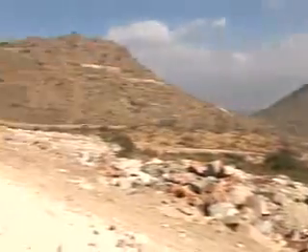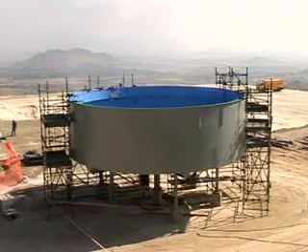Plant operations is a traditional concentrating plant for PGMs. We've got an off-take agreement for the PGM concentrate with Impala Platinum. We also produce some chrome as a by-product and have take-off agreements for that in place as well. We're building a milling and flotation plant, which consists of all your metallurgical units — your crusher section, milling, silos, and flotation plant, with filtration using a Larox filter. Extraction of PGMs from UG2 is a process where you float your sulfide minerals by adding a suite of reagents to make your sulfides, which are associated with your PGMs, amenable to float, and then you float those to acceptable grade to send to the smelters.